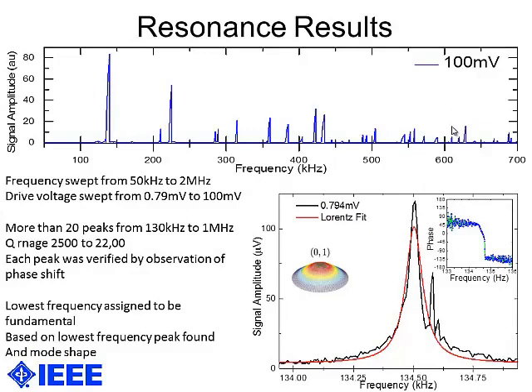Testing the diamond membrane yielded some interesting results. We swept the frequency from 50 kilohertz to 2 megahertz with drive voltages of 0.79 millivolts to 100 millivolts. The 0.79 millivolts is the lowest that the HP3577A network analyzer can output. Shown here is that wide sweep at the 100 millivolts drive, and you can see that there are many peaks up to the 700 kilohertz shown here.